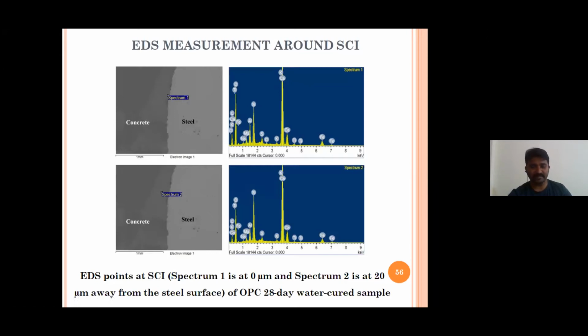Okay, so what are Ca/Si ratios? Through the Ca/Si ratio, if it is more than 1.8, I can classify that as the calcium content being high. From that, I can identify that the hydration product formed here is calcium hydroxide. And also, if the Ca/Si ratio is in between 0.8 and 1.8, I can classify that as calcium silicate hydrate. So this is given in the literature. We have selected that from the literature.